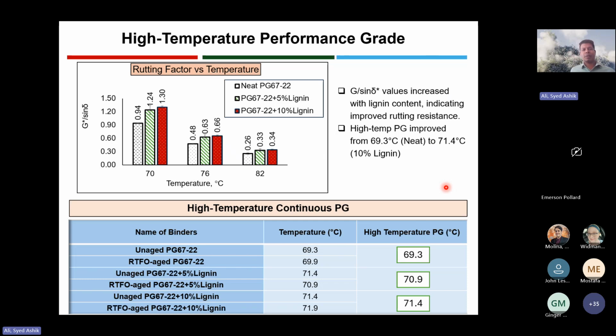Okay, here are the results for the DSR test, dynamic shear rheometer test, at high temperature. The parameter that we wanted to look at from this DSR was G star over sine delta. G star over sine delta is generally used as an indicator of rutting resistance. So what we did, we conducted the test on PG 67-22, then 5% lignin modified and 10% lignin modified binder at 70, 76, and 82 degrees Celsius.